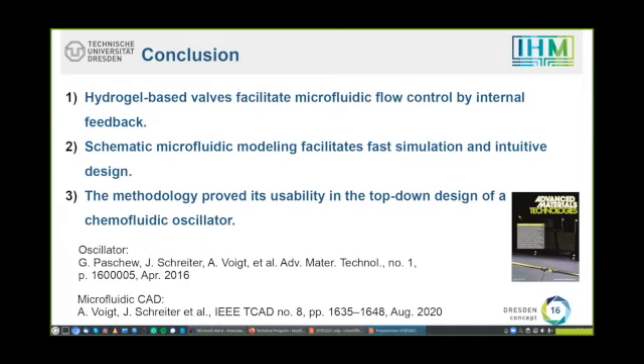Just one process question to Andreas. I don't use hydrogels anyway, so I don't know them. But the very common material in microfluidics is PDMS. And then hydrogel is another one. So in terms of process, how do you make sure that the hydrogel is where you want it to be? Is it very difficult? The simplest method is, of course, to fabricate the hydrogel first, and then for small systems you can place them manually. But what we are doing now is that we polymerize the hydrogel on a glass slide, and then fabricate the channels in another layer, and then we can do a flip chip technique that we basically connect the slide where the hydrogels are attached to the layer where the microfluidic channels are.